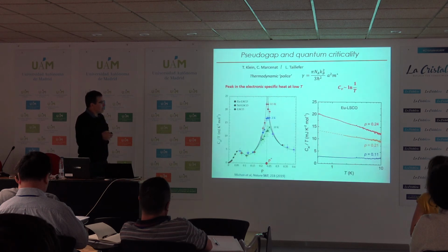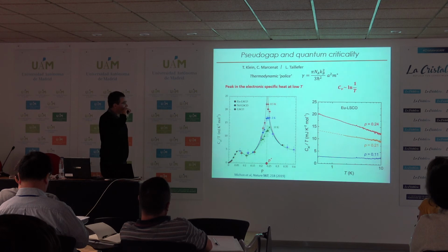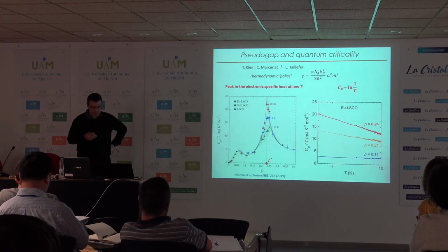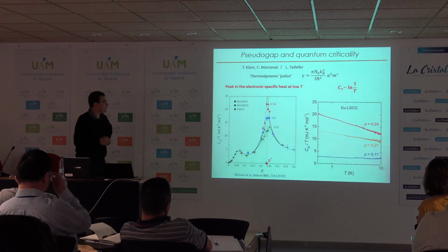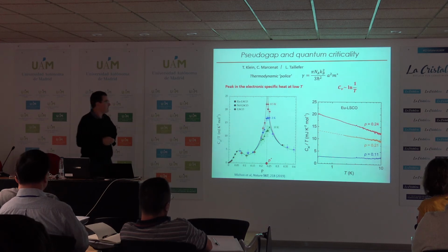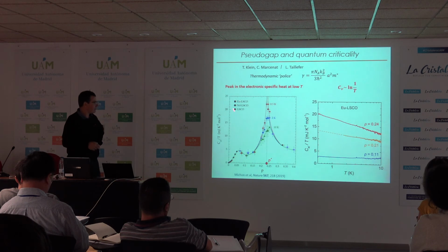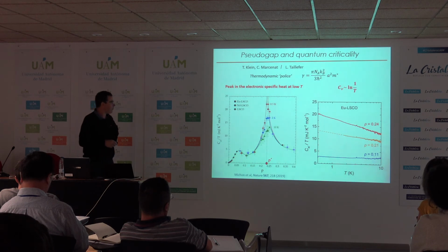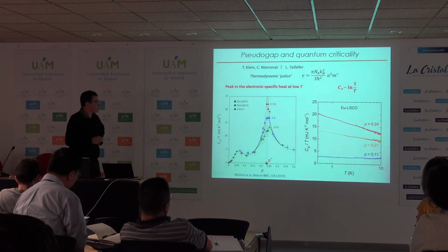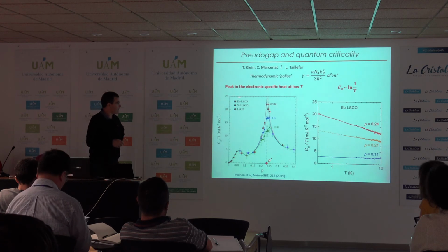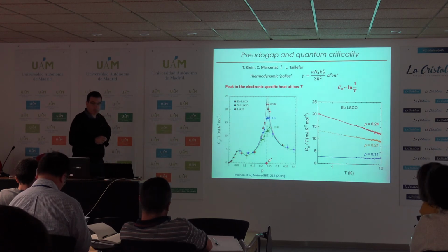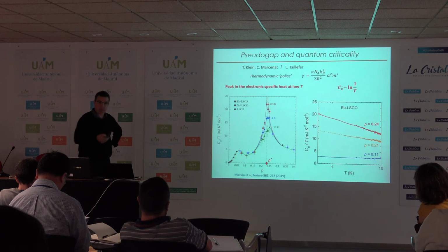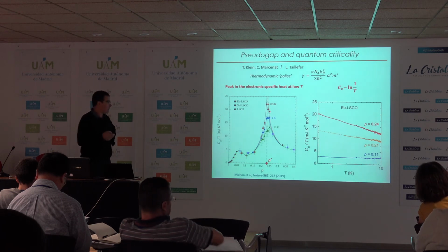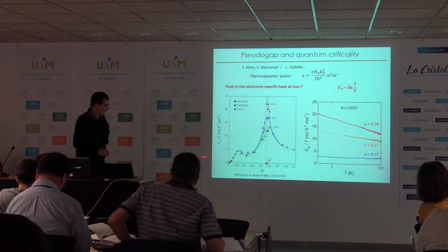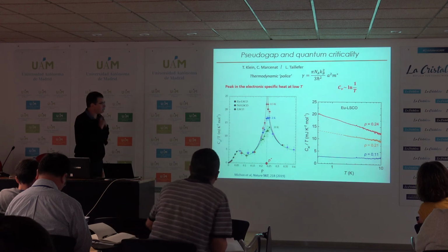Okay, so now let me discuss some measurements obtained by the group of Louis Taillefer, Thierry Klein and Christophe Marcenat in Grenoble, where they measured specific heat in the LSCO family, mainly in Nd-LSCO and Eu-LSCO. The good point with these compounds is that Tc is low, Hc2 is small, and they can easily measure in the normal state across the whole phase diagram.